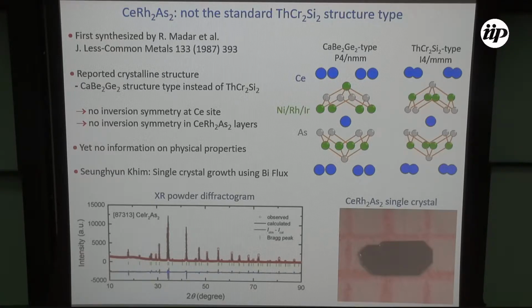The important aspect for us is that you lose the center of inversion symmetry at the cerium site, and also in the cerium layers. In total, the structure has an inversion symmetry, but not locally on the cerium site. It's an old compound, first synthesized more than 30 years ago by a chemist who found the structure, but the physical properties have not yet been reported. And Seunghyun Khim was able to grow single crystals using a bismuth flux.